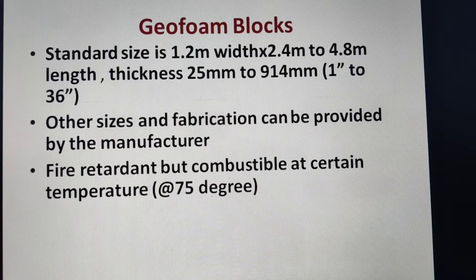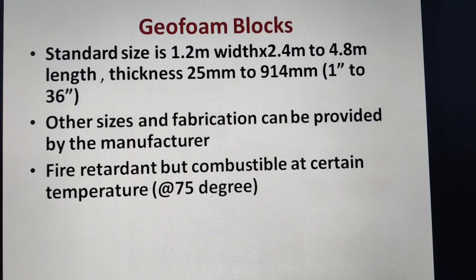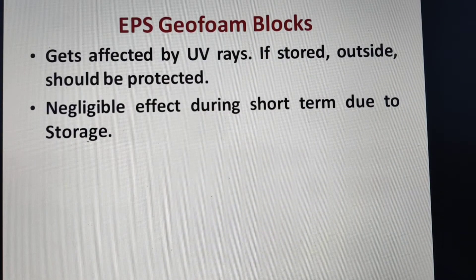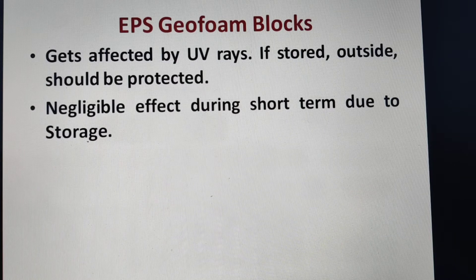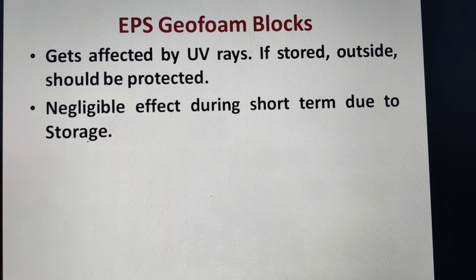These blocks are combustible — though said to be fire retardant, they are combustible at around 75°C. They are also affected by UV rays due to their polymeric content, so if stored outside they should be protected. When stored inside or used in construction, there is negligible UV effect.